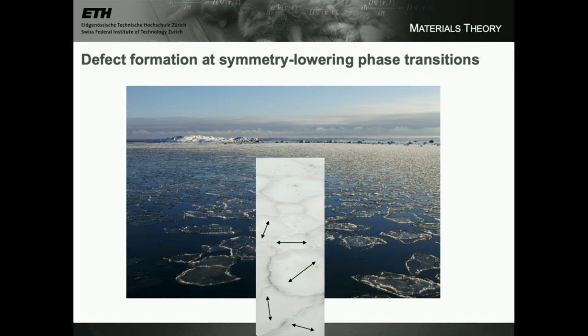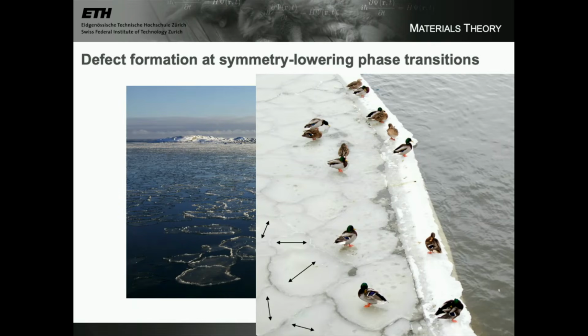The last point to mention is that associated with these defects is often a functionality. And so we saw already in the case of yttrium manganite, there was a conductivity associated with these domain wall defects. In the case of the ice, the ducks, you can see, sit in the middle of the platelets because the food gets stuck at the intersections. So the functionality in this case, I guess, is algae, which are at the defects. So three properties of symmetry-lowering phase transitions. They lower the symmetry, there's defect formation, and these defects have functionality.